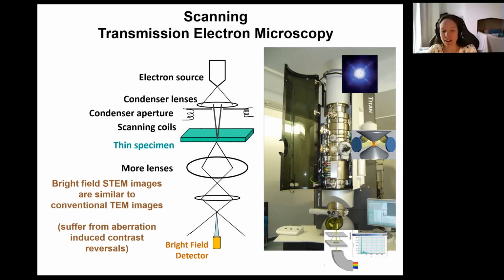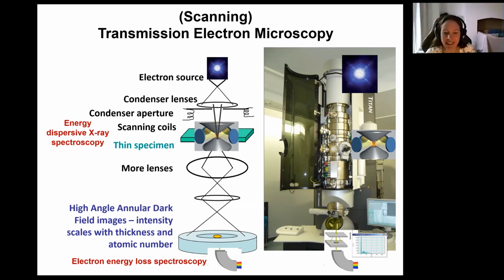But the problem with bright field imaging in the TEM or the scanning TEM is that it suffers from something called contrast reversals. So when you're down at the atomic resolution, sometimes atoms will appear white and sometimes they will appear black, and that makes interpretation more challenging. So a really popular imaging mode in the scanning TEM is this one called high angle annular dark field, or sometimes just annular dark field. And that's really popular because it uses Rutherford scattering, and therefore we have a high intensity signal where we have scattering from an individual atomic center. So when we're looking at atomic resolution image, regions that appear bright will be the positions of the atoms. And even better than that, this technique has Z contrast sensitivity, so it's sensitive to the atomic number. And that means if we know the thickness, we can work out the atomic number of our material.